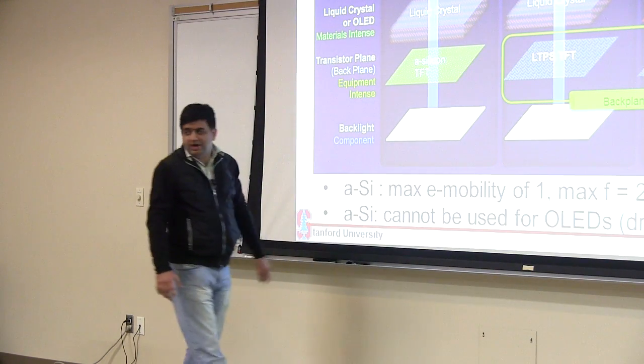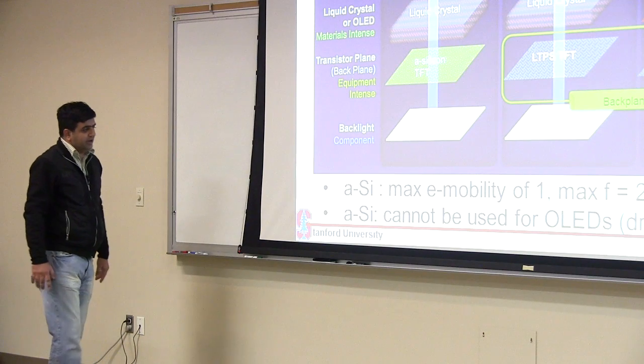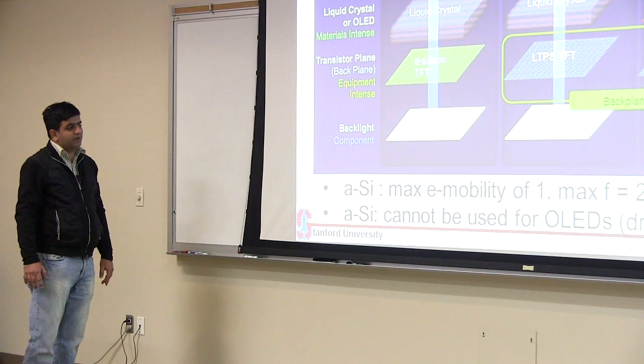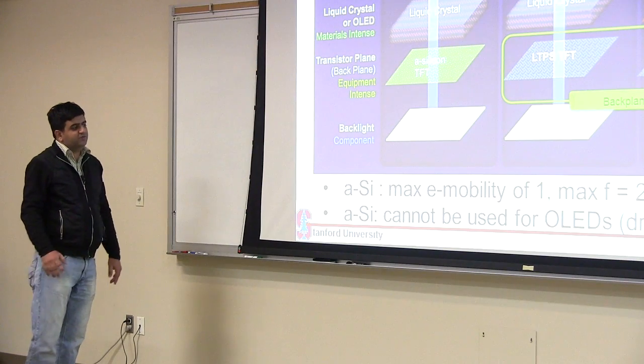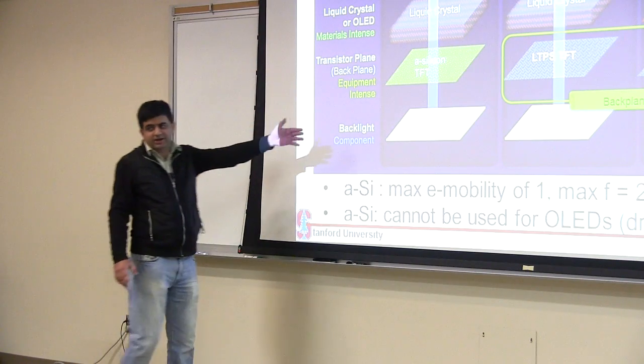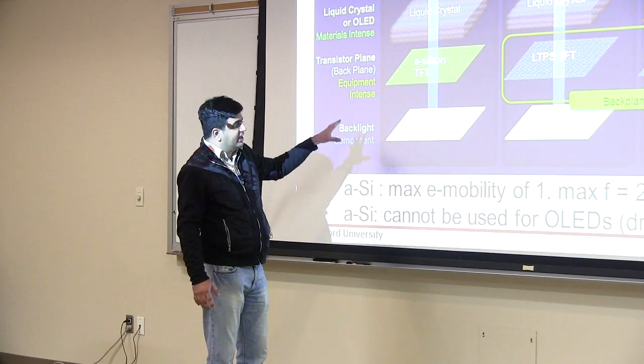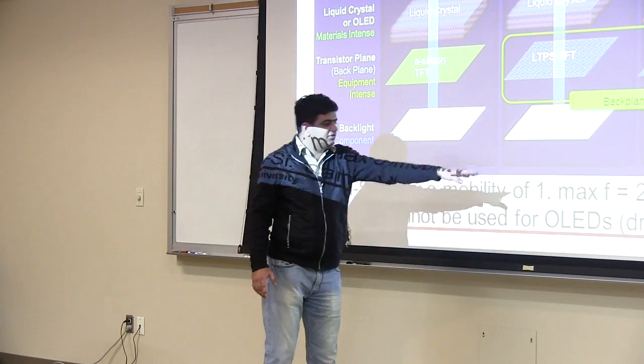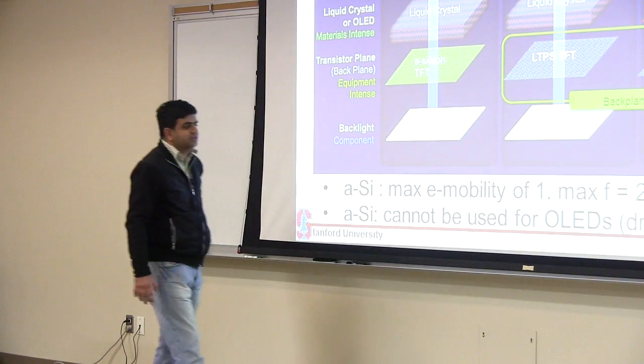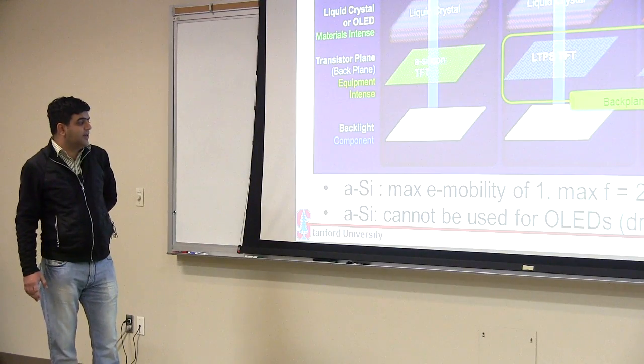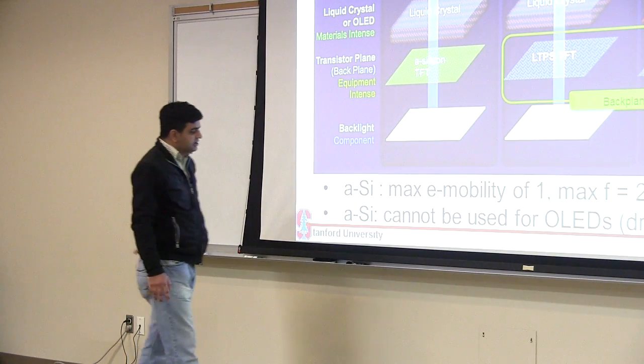The running horse or the staple technology so far in the industry has been amorphous silicon because you can deposit it very easily on glass. But it comes with a maximum mobility of one. We talked about mobility when we talked about transistors and FinFETs, but it's equally important in something as big as display. And this mobility of one only gives you a frequency, maximum frequency of 240 hertz.